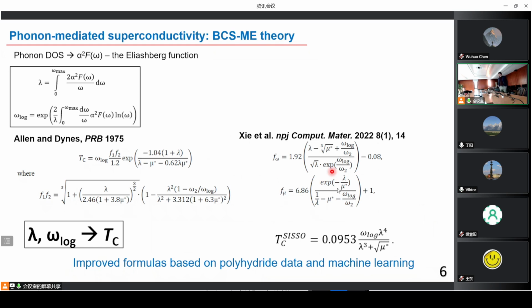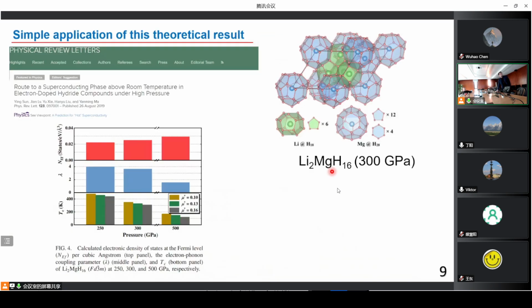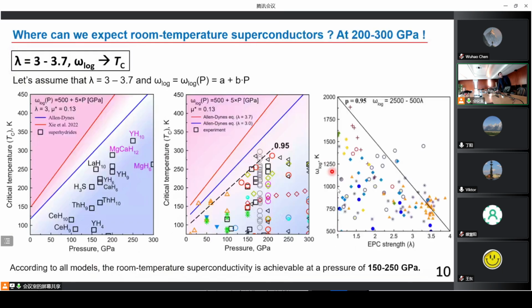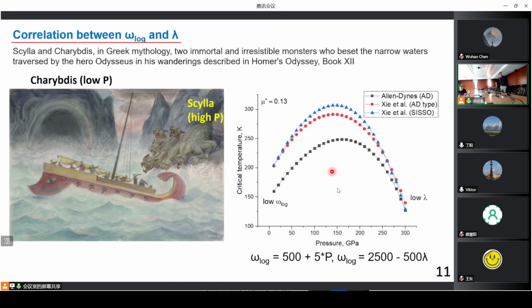Maybe a naive question. When you say that there is a maximum for the electron-phonon coupling and the TC, right? Naively, I would have thought that high electron-phonon coupling is actually good for TC. Yes, definitely good. So why should there then be a maximum in lambda? The problem is that we have two parameters at the same time, and they have negative correlation between each other. In such a situation, it will always be a parabola.